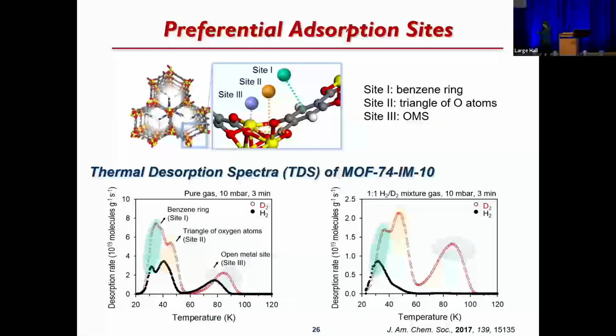As we know, there are many adsorption sites, hydrogen adsorption sites, on the surface of a MOF. The first site can be the benzene ring. The second site will be the triangle of oxygen atoms. The third site is the open metal site. And from the thermal desorption spectra, we clearly see the three different sites. And interestingly, from the experiment with a 1-to-1 hydrogen and deuterium mixture gas at high temperature, this corresponded to the open metal site, and at the open metal site, only deuterium can be adsorbed. It means that at high temperature, we can have very high selectivity.